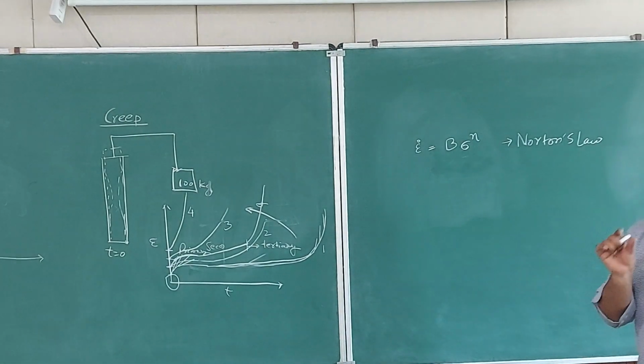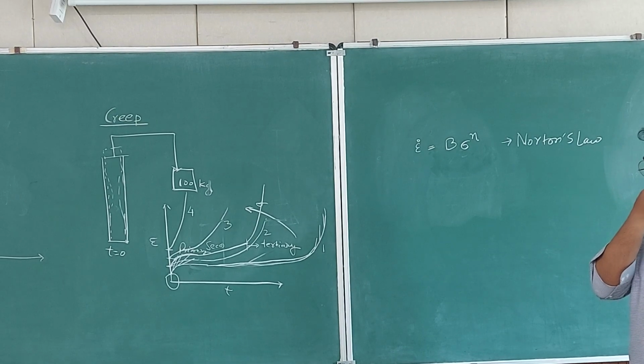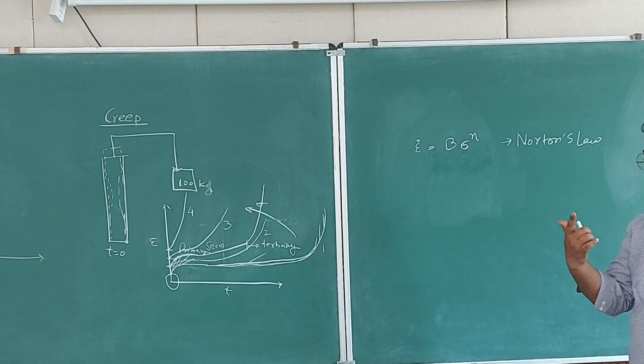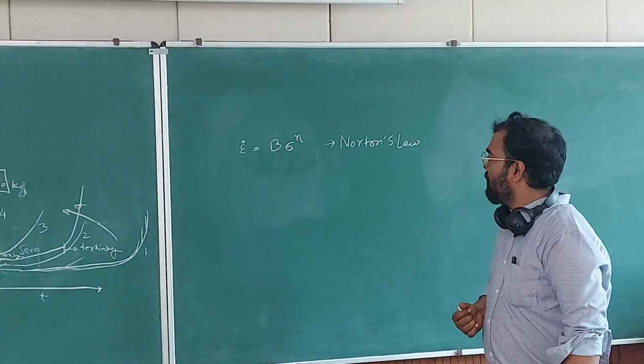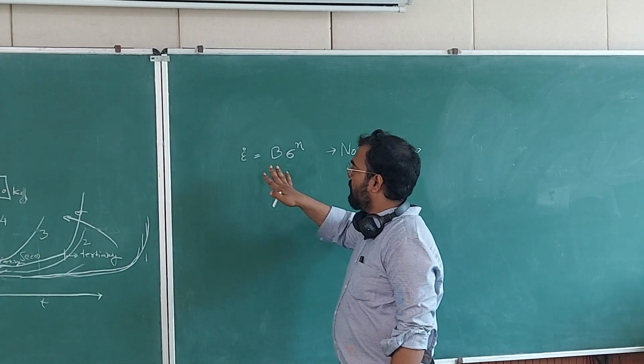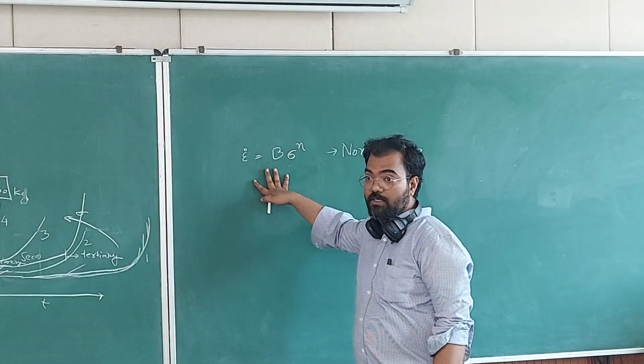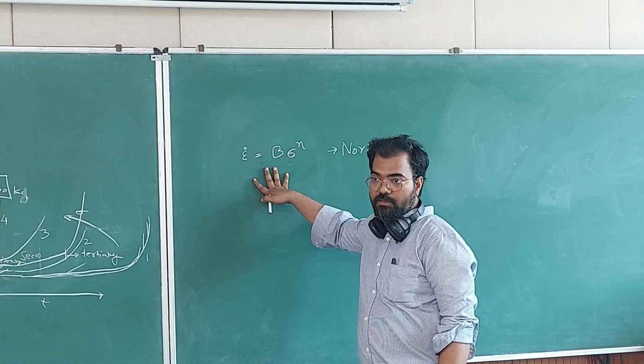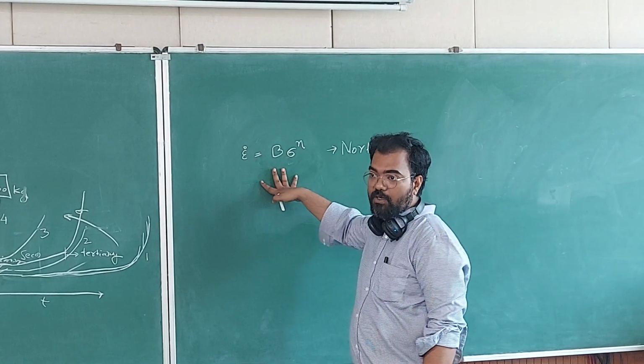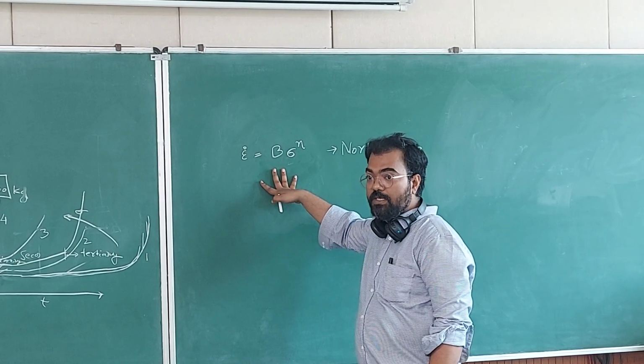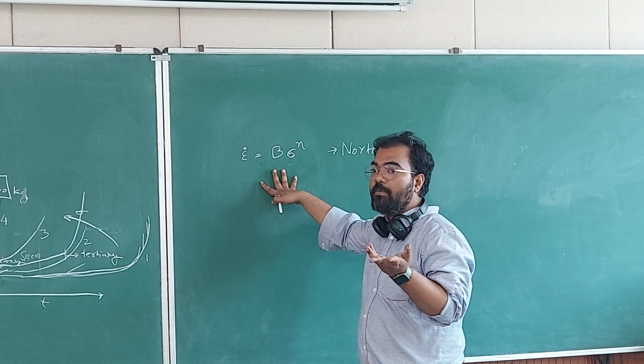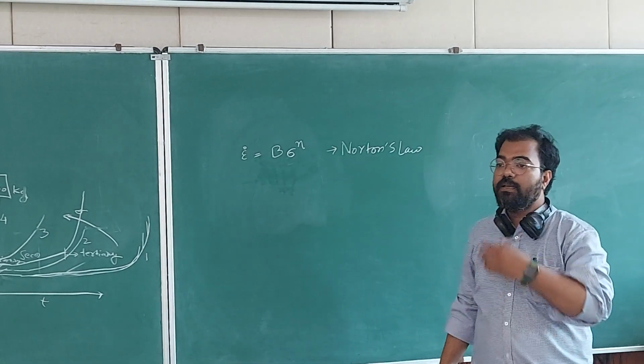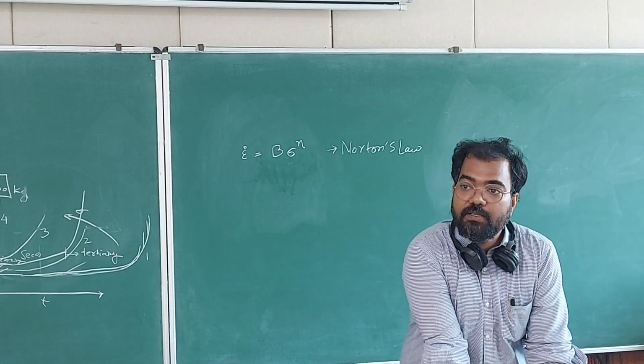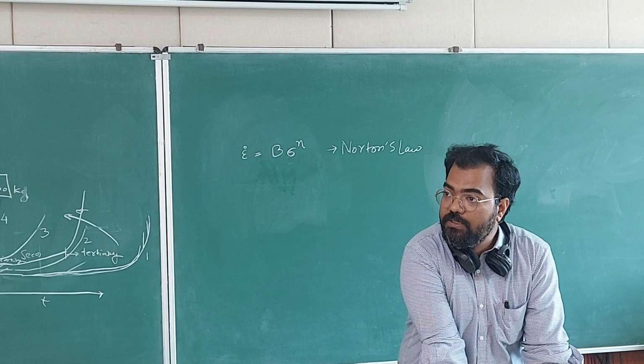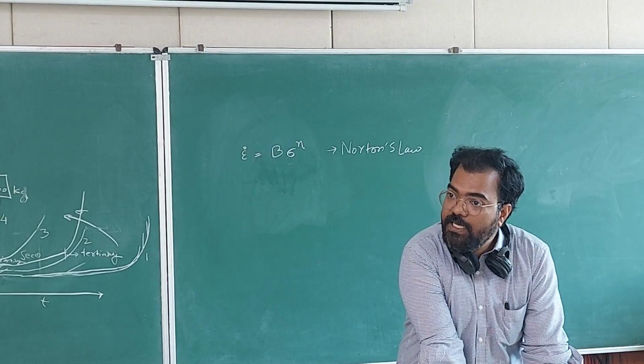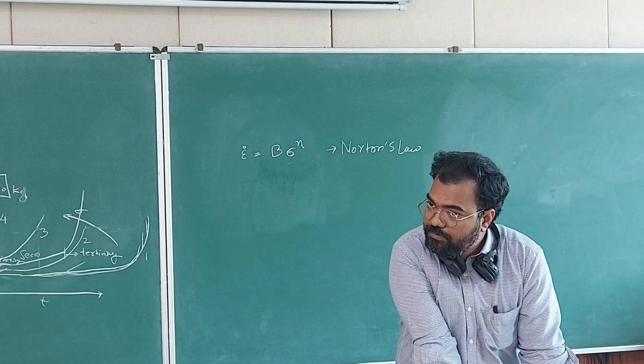Okay, in this case B can be defined differently. So B can have different meaning, N can have different meaning. Okay, and if this is followed, then strain rate is not a function of time. Right? In this law, strain rate is not a function of time. So this mostly will be happening in, why mostly? It will be happening in secondary creep only. Right? If you have to make it something like this for primary, then you have to make N or any of the other parameters time dependent. Then it will be describing different stages of the creep.